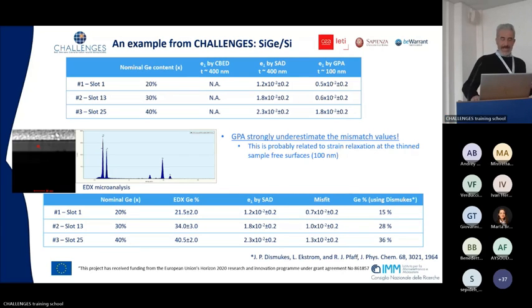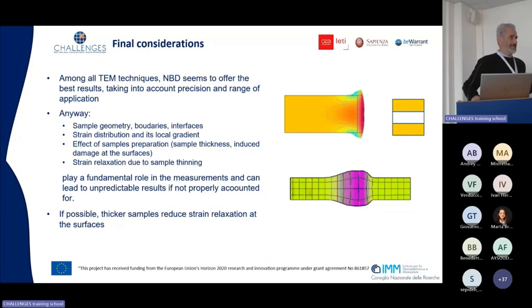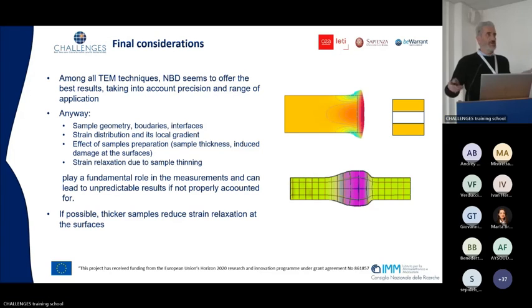So you can use whatever technique you want. Some are better, but sample preparation is the ultimate limit, of course. You can end up with strain relaxation that completely lowers the accuracy of your measurement. This is what we saw before. You can have strain relaxation. This situation in which you have a cap, a substrate, a strained region, and then again a cap is much more favorable to strain analysis.